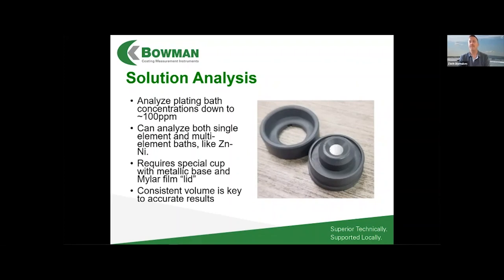Then you lay a piece of mylar over the top of that, and you snap that other piece on top. A little bit of the solution will overflow into that little rim around there that catches any extra drops of solution. Then you've got a consistent volume inside of that little shiny area. The reason there's a metal there, typically molybdenum, is because the solution is going to scatter the X-rays quite a bit, as it's a light matrix material. Having molybdenum as the base gives you a nice smooth background. It absorbs a lot of those scattering X-rays. And not many people are plating material like molybdenum, so it doesn't interfere with the actual analyte that you're measuring. We can measure down to a concentration around 100 parts per million.